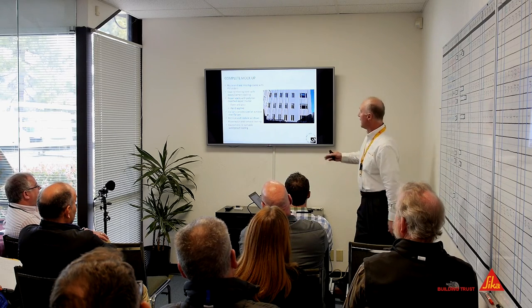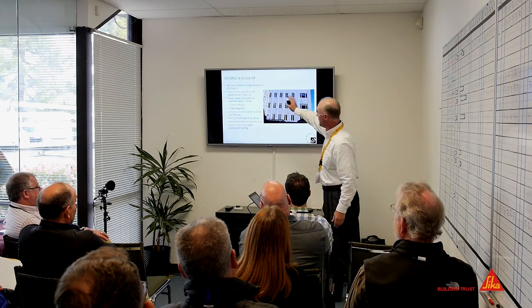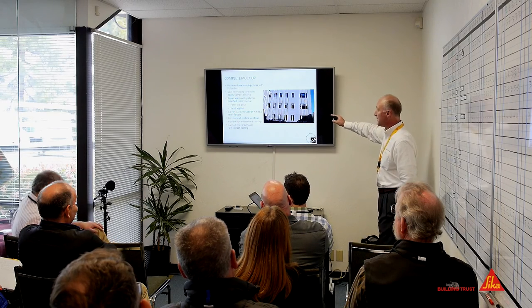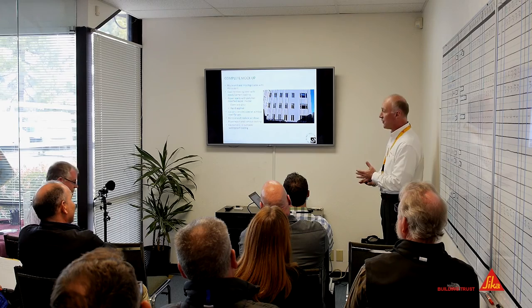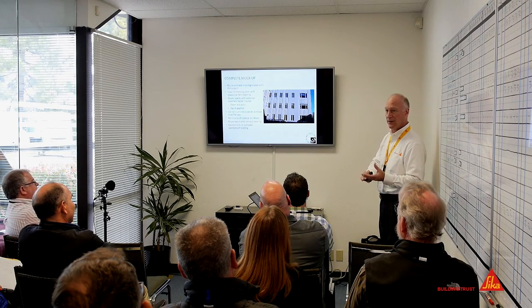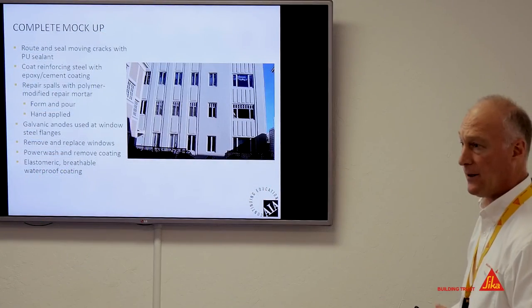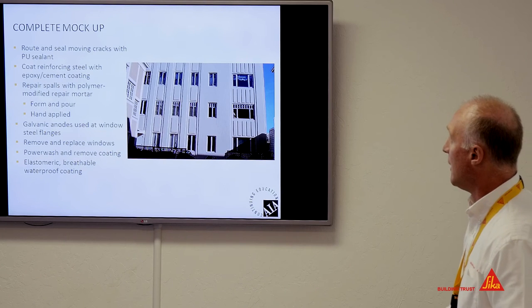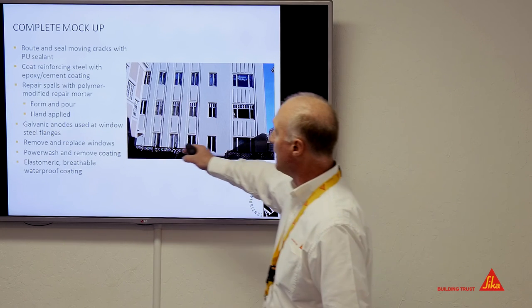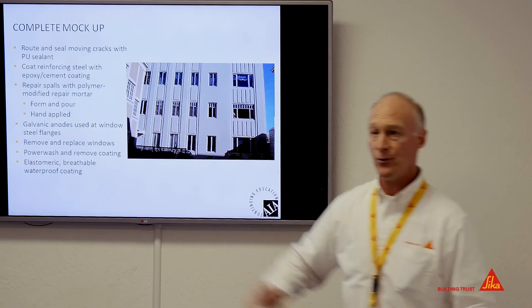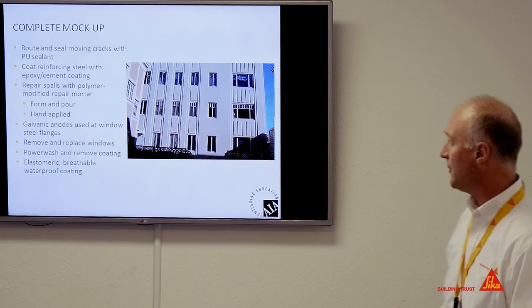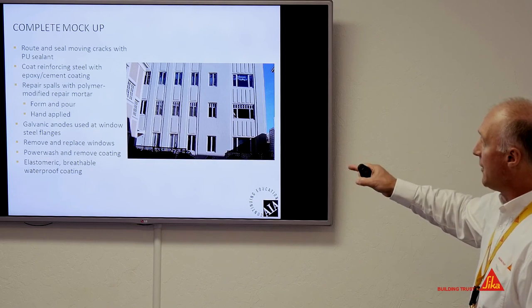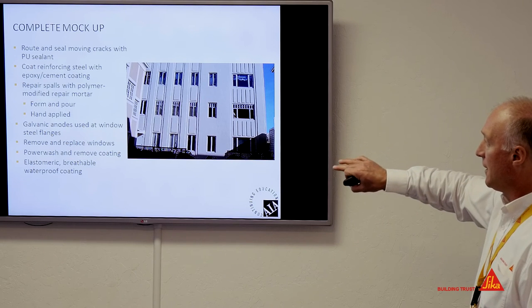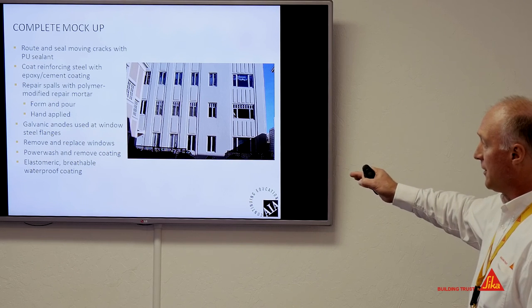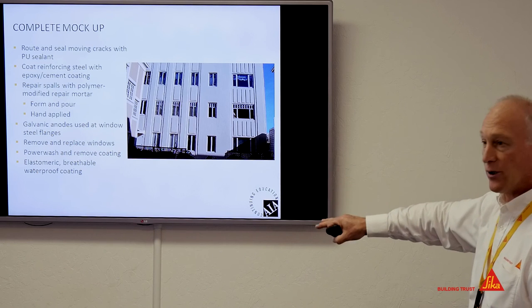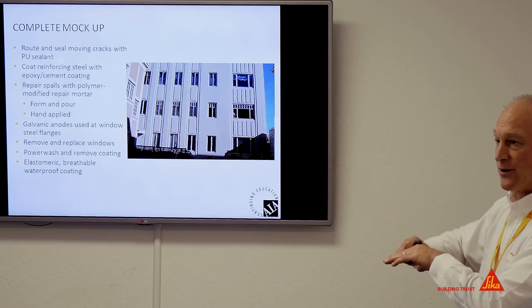And so what they did was they were going to route and seal all the moving cracks with a urethane sealant, coat the reinforcing steel with an epoxy cement coating. You'll see that out and back this afternoon. They had form and pour and hand applied repair materials where they were going to use polymer modified cement repair materials. They were going to use galvanic anodes around the windows. In some areas, they were going to remove and replace the windows, power wash, and then do a coating. And that was the sequence that was defined.